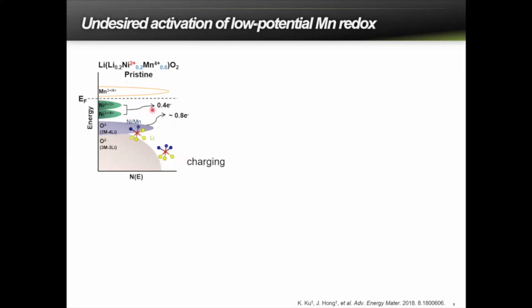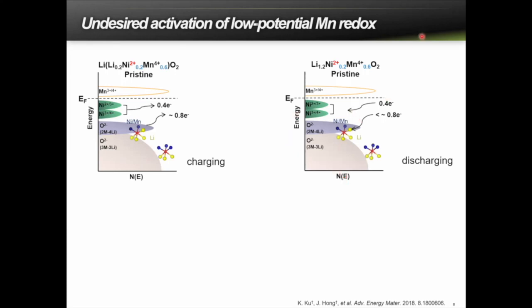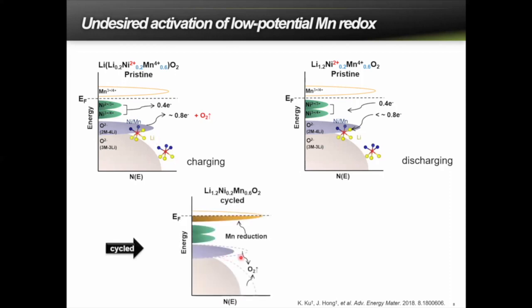First, during the charge, when lithium is extracted, electrons are extracted from the nickel cation redox reaction, contributing about 0.4 electrons, while the remaining 0.8 lithium ions are deintercalated with oxygen oxidation. So in an ideally reversible situation, the discharge reaction is going to be exactly the opposite reaction. On the other hand, if there is a loss of oxygen during the oxygen reaction in the charge, the oxygen states will be partially lost, so that during the discharge reaction, some of the originally unoccupied states like manganese will participate in the reaction. And it is well known that the manganese 3+/4+ redox reaction is low in potential and typically triggers the formation of spinel-like structure.